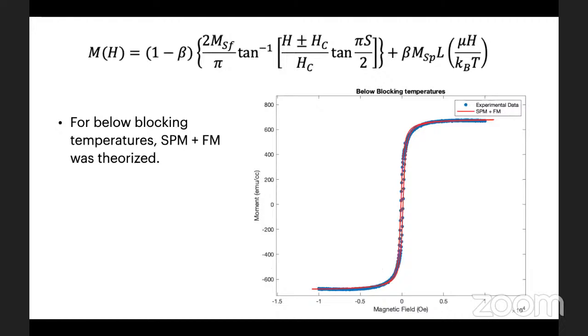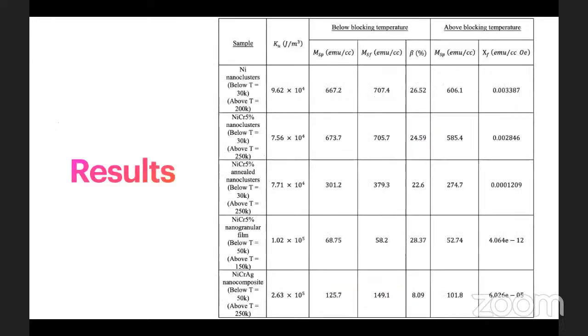Now, for below blocking temperatures, since there is more coercivity, we can theorize that FM contribution is dominant. But since there would also be SPM contribution in minimal amount, we utilized SPM plus FM here and carried out the fit, which is showcased on the right side. This fit actually assured that our theory was on a good basis. And finally, these are the results that I conclude on.